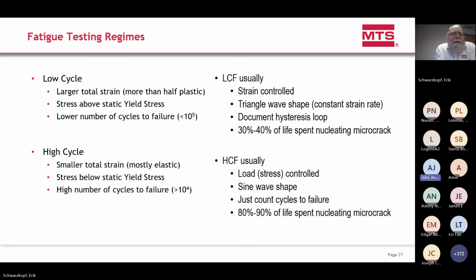So let's just review what's going on so far. We have low cycle fatigue, which is strain oriented, and usually the strain is plastic. More than that, the total strain is what is being controlled, but some of that total strain is plastic, usually a significant chunk. Those stresses achieved during a low cycle fatigue test are usually above the yield stress, and it's a low number of cycles to failure in these low cycle fatigue tests.